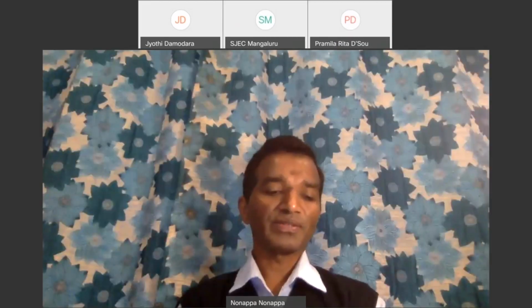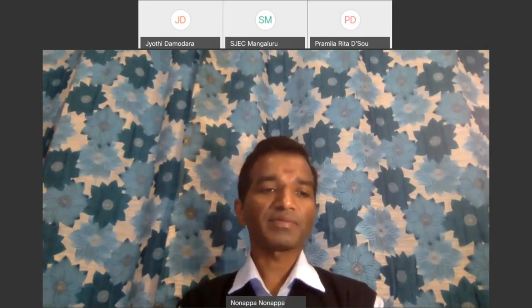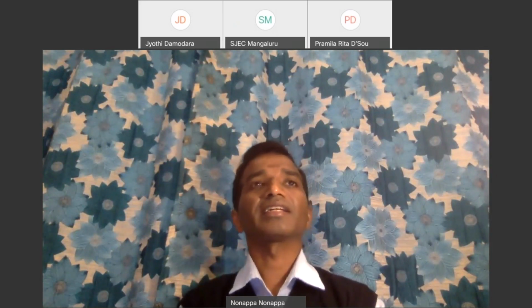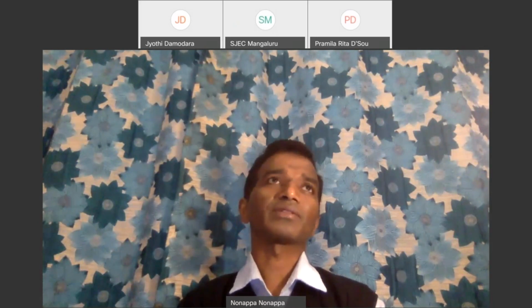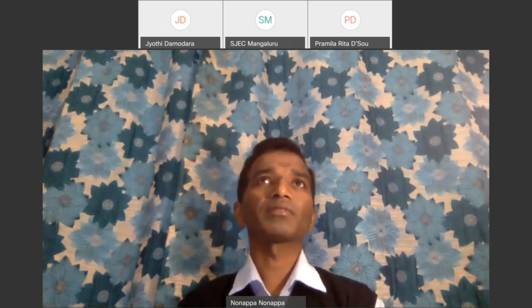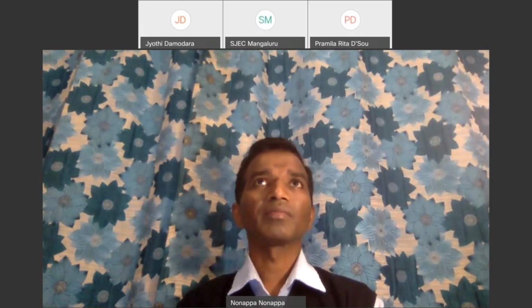No, electron microscope is only to see what type of structures are there. And generally, as any sample you deal with the electron microscope, they undergo beam damage. This is a common phenomenon. For example, if you are using scanning electron microscope, you anyway treat the samples with an extremely thin coating of gold palladium. But if you want to do transmission electron microscopy, they have to be very thin, and they're sliced, and they undergo beam damage. Of course, there are ways to overcome this using low voltage.